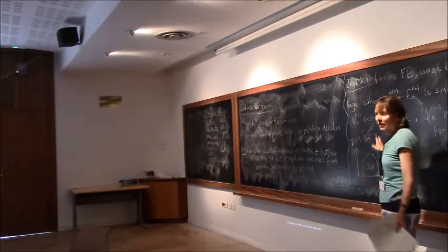Questions? Yeah. So we can apply this principle to all perovskites since we have TiO6. So, I mean, you can apply this principle to anything. This electronic structure is, simplistically, the electronic structure of any D0 perovskite, right? So barium titanate, lithium niobate, lead zirconate: the valence band is made primarily of oxygen 2p, and the conduction band of empty D states. I'll show you some real electronic structures in a moment. You'll see that's a little bit simplistic, but basically that's the density of states of any perovskite.